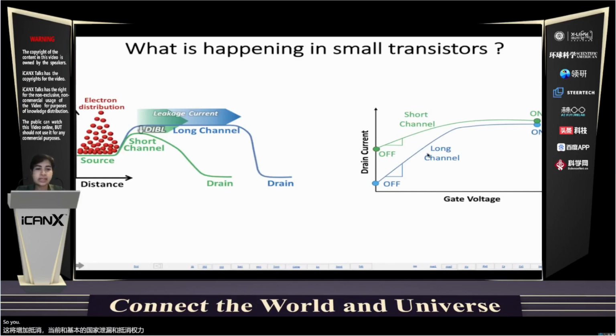So as you can see in the curve here, the blue curve is for a long channel transistor. You can see the steepness of the curve here is good. That means the subthreshold swing is smaller. The steeper the curve, the smaller the subthreshold swing, because it's the voltage required to increase the current. And when you make the transistor smaller, because of this effect, which we call a short channel effect, the leakage current has increased, and you can see the subthreshold swing has degraded.